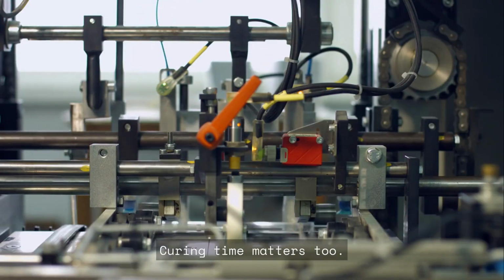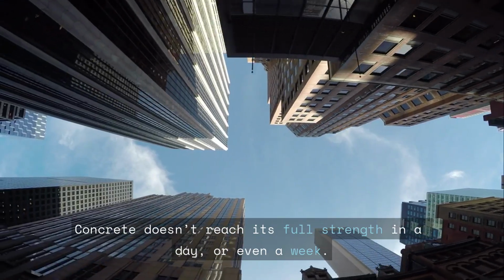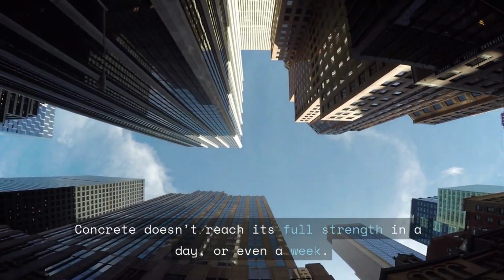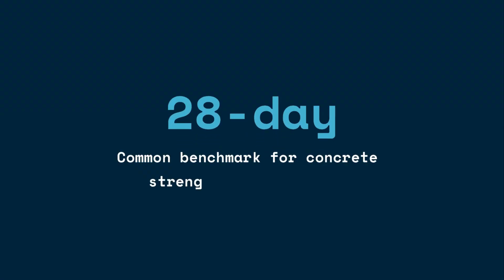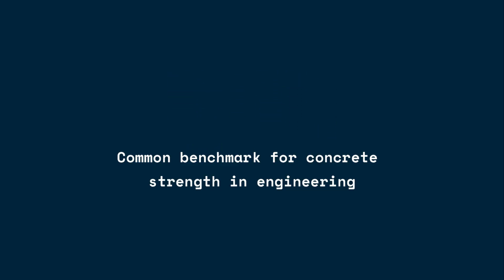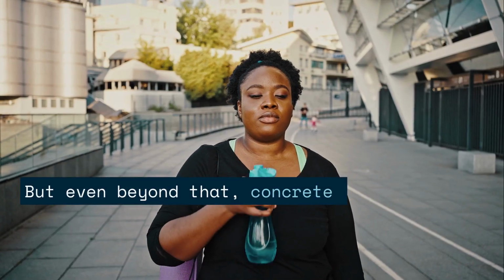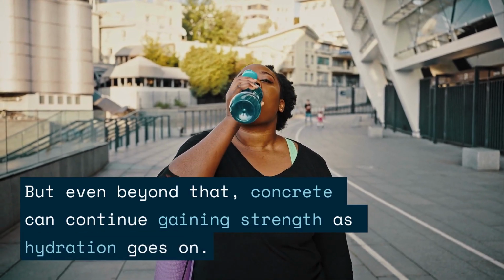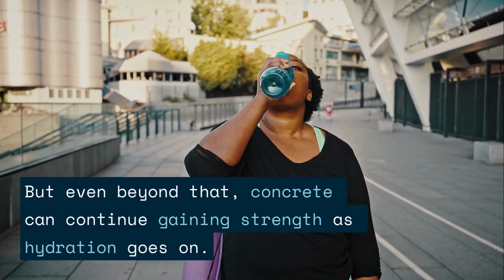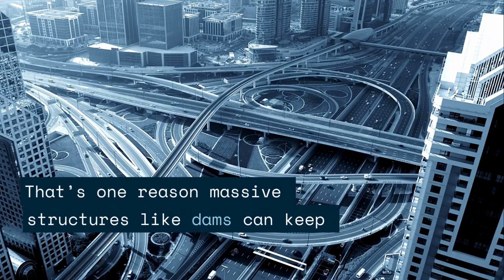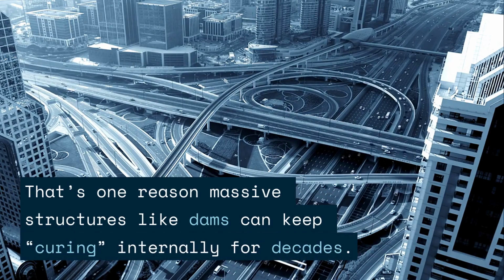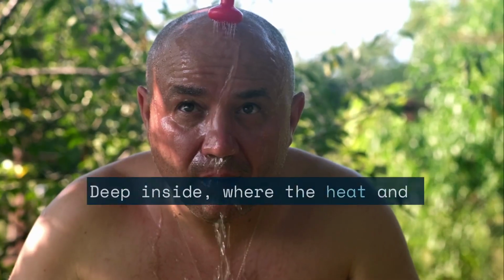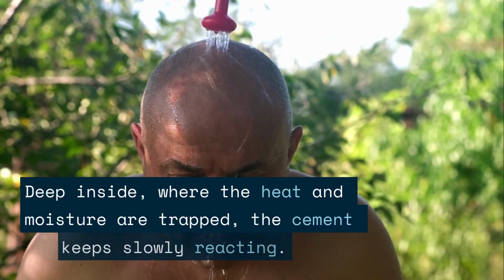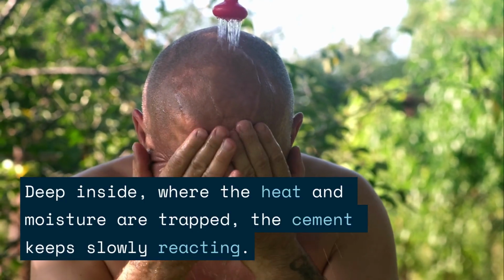Curing time matters too. Concrete doesn't reach its full strength in a day or even a week. A common benchmark is its 28-day strength, the value engineers use when designing structures. But even beyond that, concrete can continue gaining strength as hydration goes on. That's one reason massive structures like dams can keep curing internally for decades. Deep inside, where the heat and moisture are trapped, the cement keeps slowly reacting.